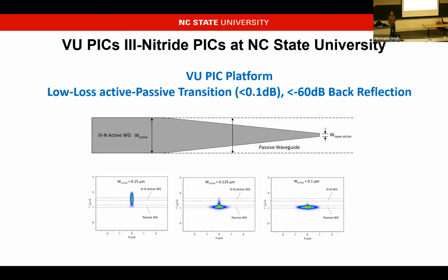And one of the things we've been doing, as we've been learning about what materials we're able to put together in combination, is building and designing what would be our platform for the visible and ultraviolet PICs. This shows an active, so not only a laser gain region that's going into a passive waveguide in a stacked structure. Again, we're going to build this by breaking the device in half, processing it, and putting it together. You can see that we can have a mode transition that goes from the active to the passive. I didn't show all the modeling results here, but we can make this transition with less than 1/10 of a dB insertion loss, and most importantly, with less than 60 dB of back reflection. This actually winds up being really important. For the people trying to make a lot of these PICs for quantum photonic applications, the devices are really limited by back reflections in the device.